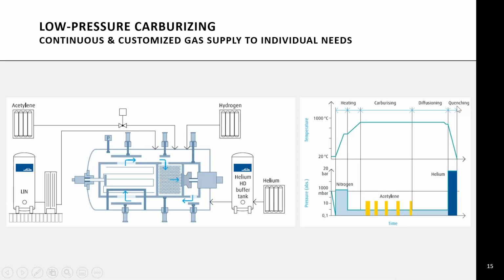Yeah, thanks, Jack. So low pressure carburizing compared to conventional carburizing allows operators to increase their temperatures and shorten the total process times, kind of similar to what Jack was mentioning about nitrocarburizing as well. In combination with high pressure gas quenching, the solution minimizes distortions compared to normal oil quenching. It ensures consistent cooling results with respect to grain structure and hardness. In low pressure carburizing, the optimal selection of gas purity is important also for achieving that outcome.